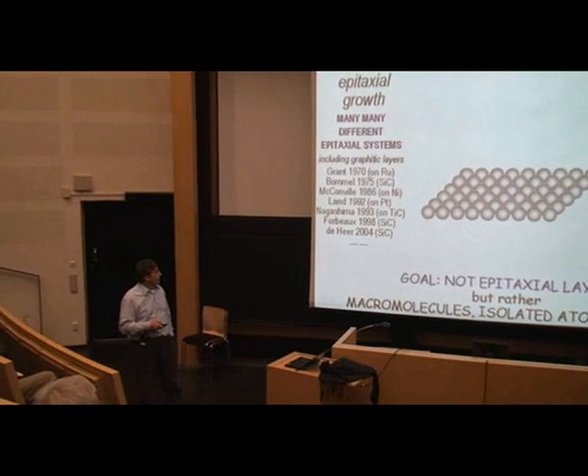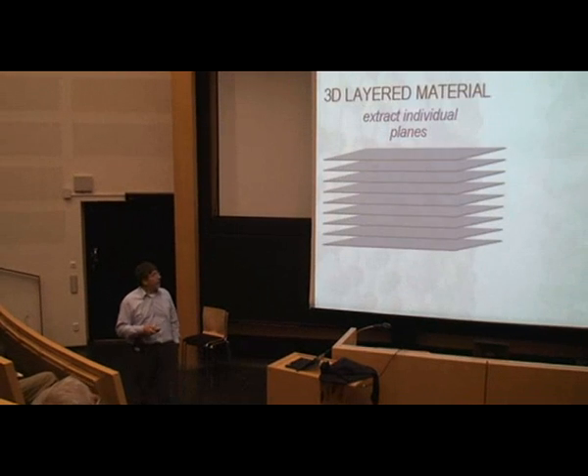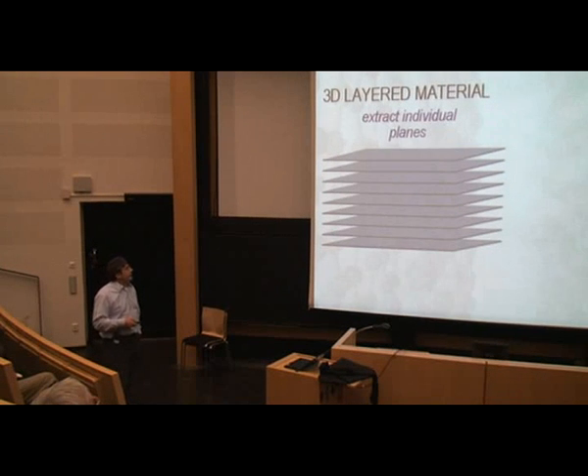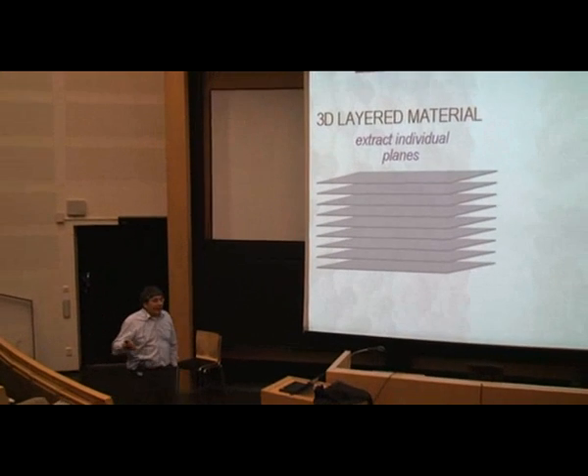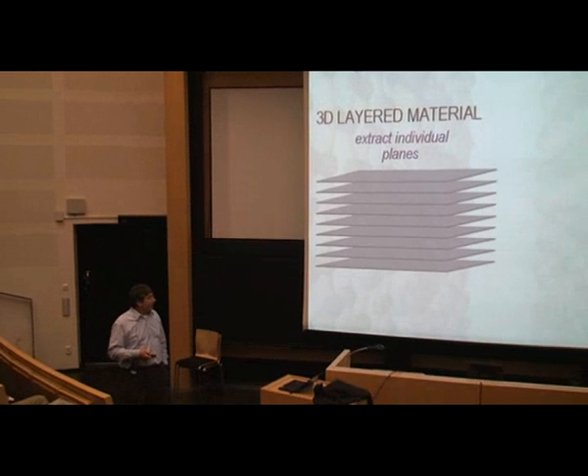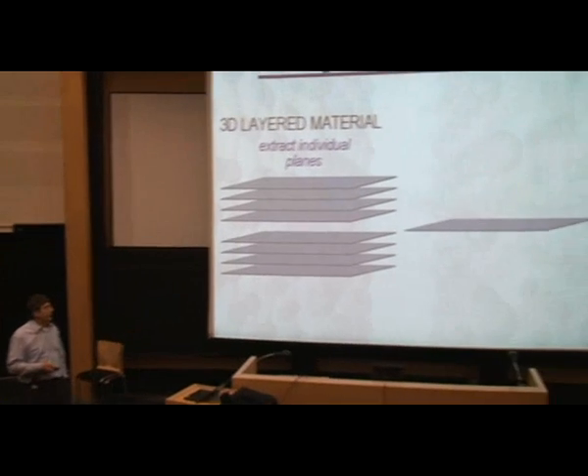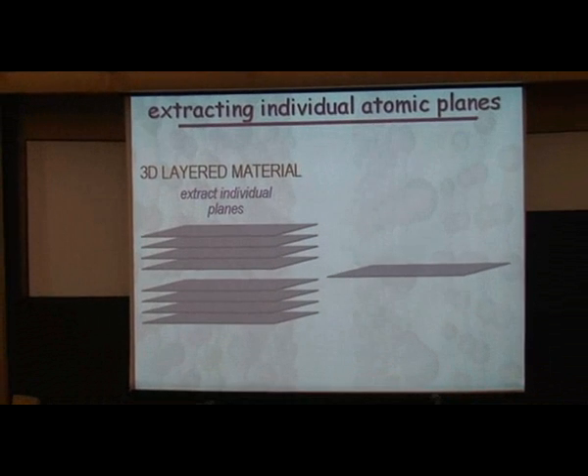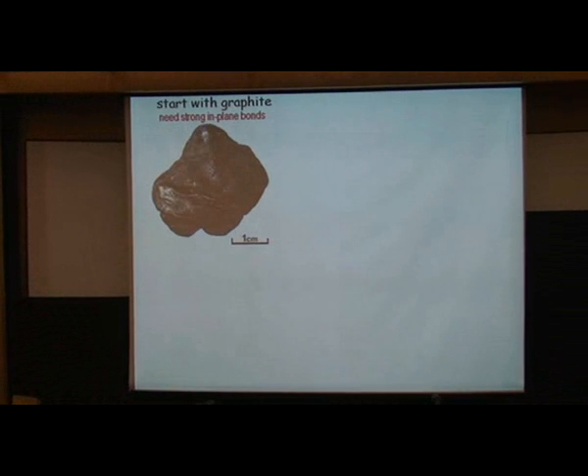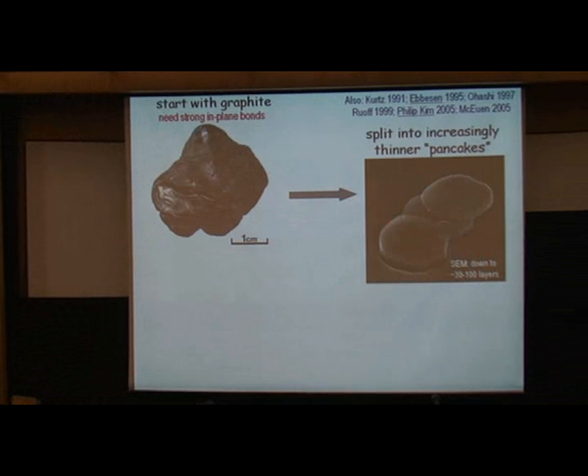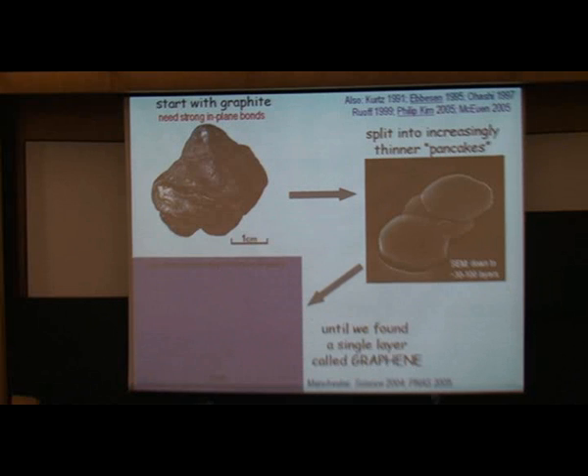So the poor man's approach: okay, you don't know what to do, you levitate a frog. In this case we thought, okay, we can't do it by etching, can't we do something else? Exactly as I told you, pull out individual atomic planes. It's not as difficult with hindsight. What you do, you take a bulk graphite sample and start chopping it like a butcher into thinner flakes, and you can really easily go directly down to something like 30 to 100 layers. People before and after us made these sort of observations. What we did actually went further.